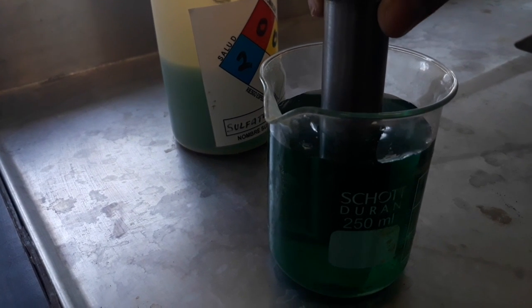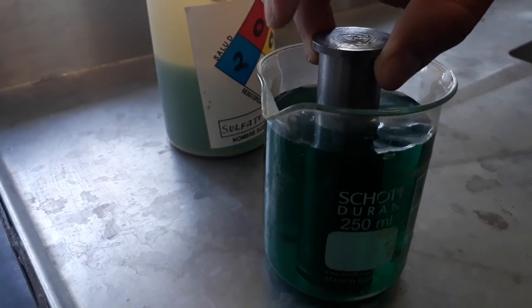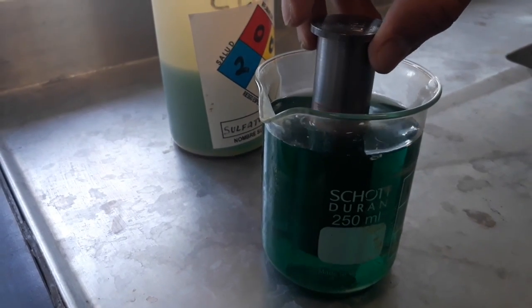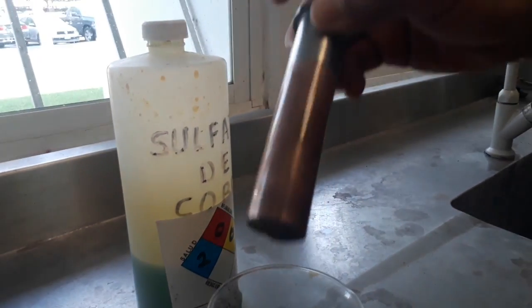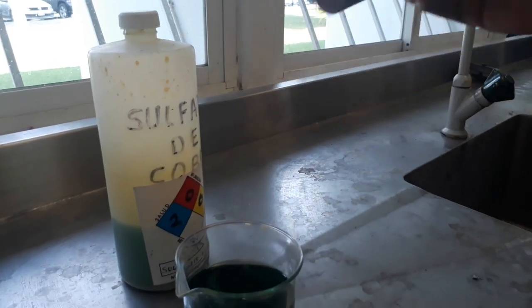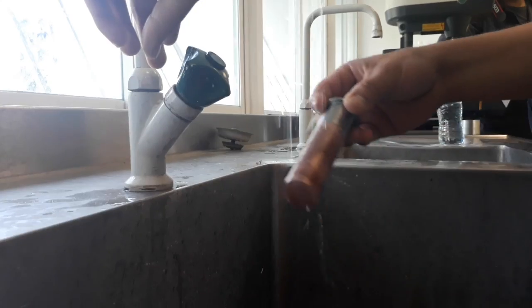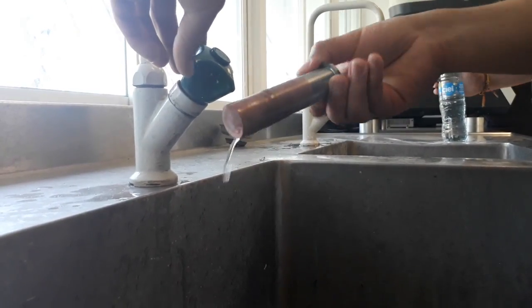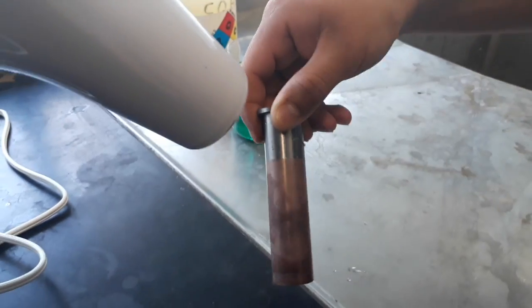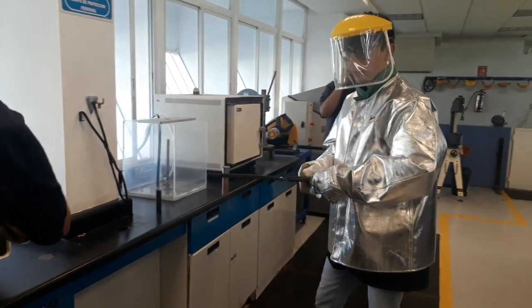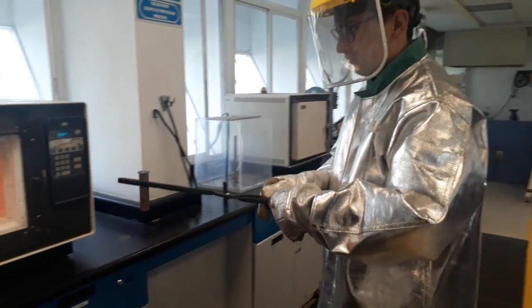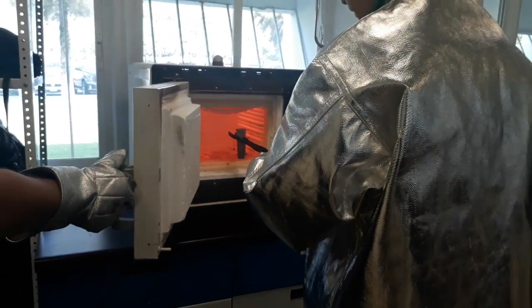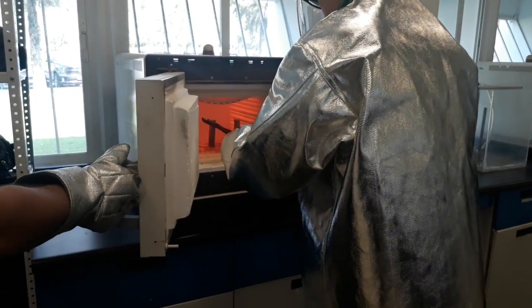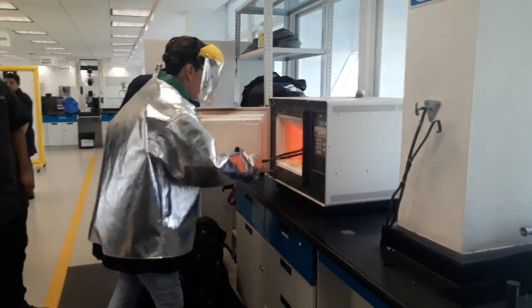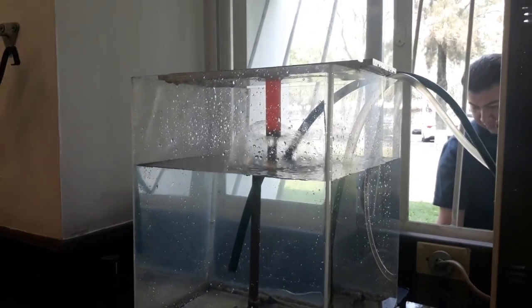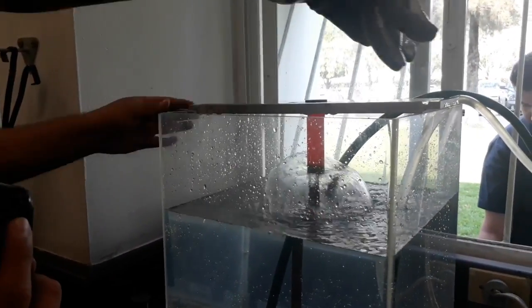For this practice, we have a 1018 steel, and then we prepare a 400 milliliter copper sulfate solution, and we introduce the steel into the solution. After that, we took it out and we started drying it with hot air. Then we insert the piece into the oven at a temperature above 727 Celsius degrees. Then we took it out and we moved it into the Jominy device in order to cool it at a certain cooling rate.